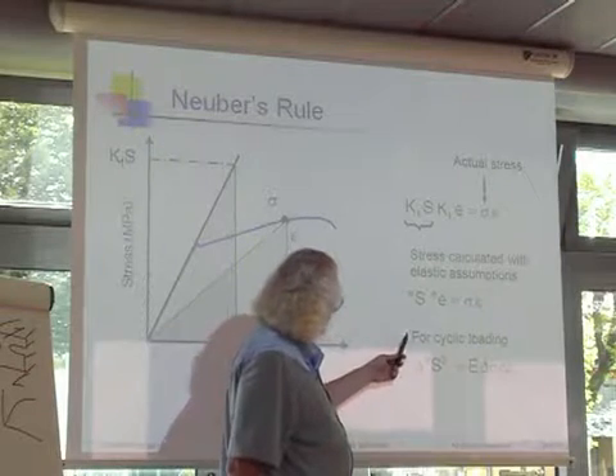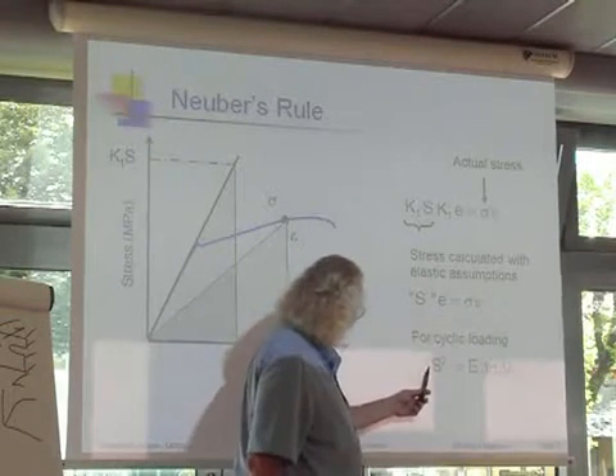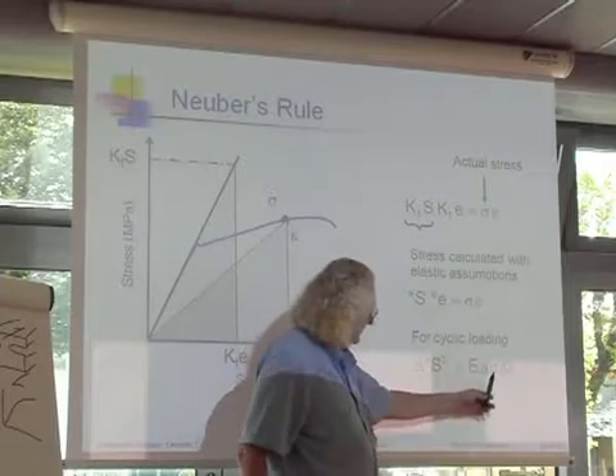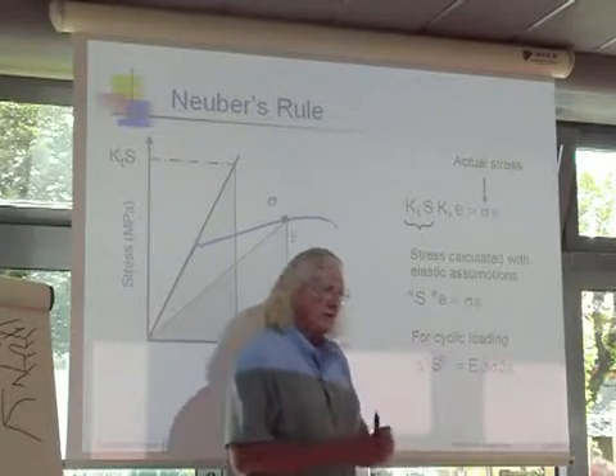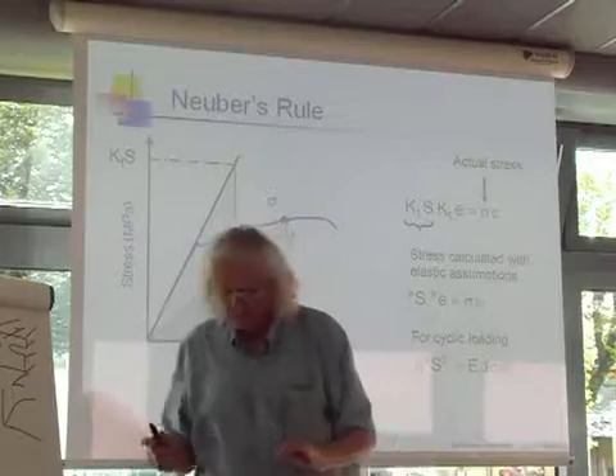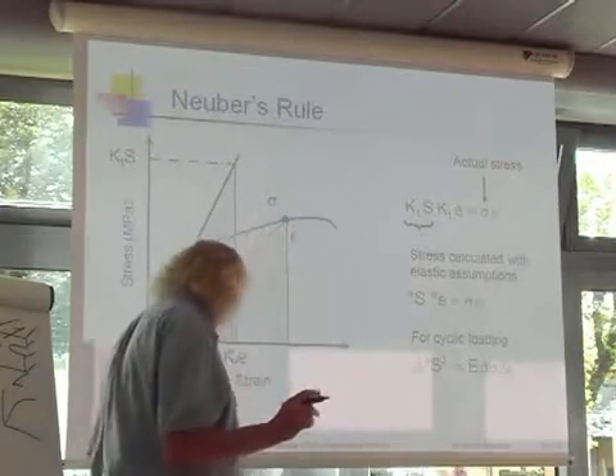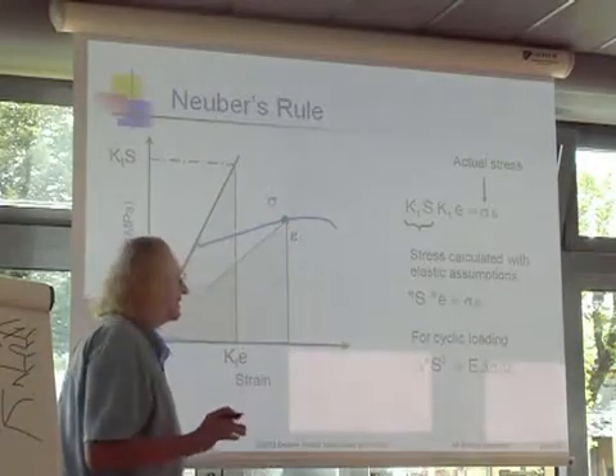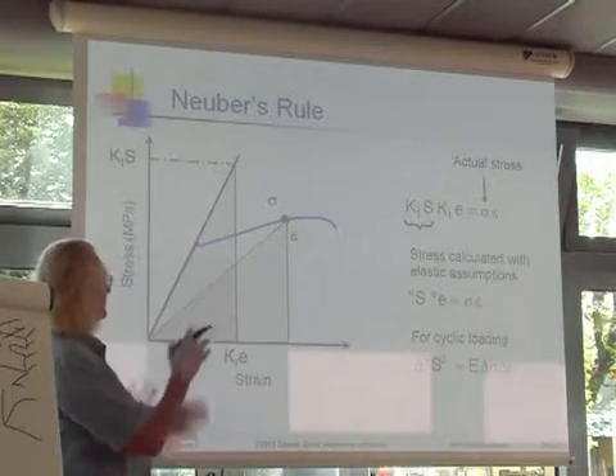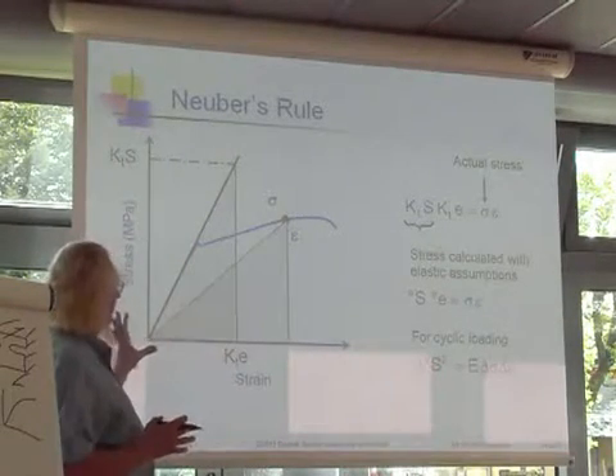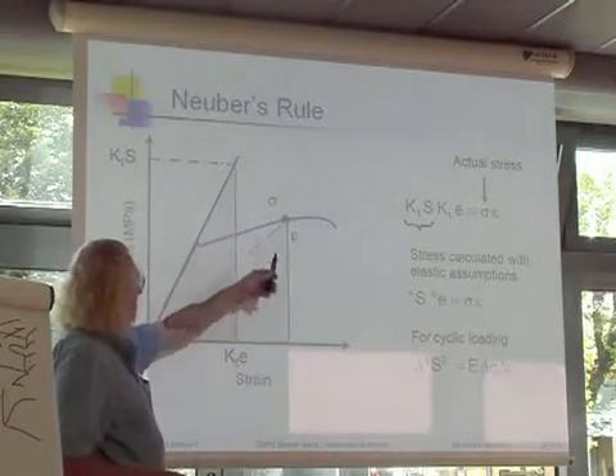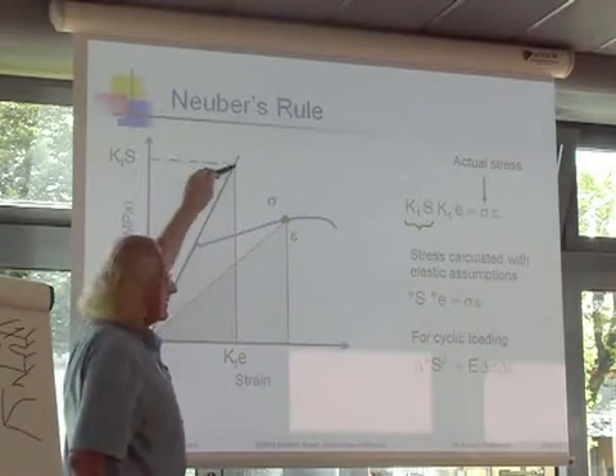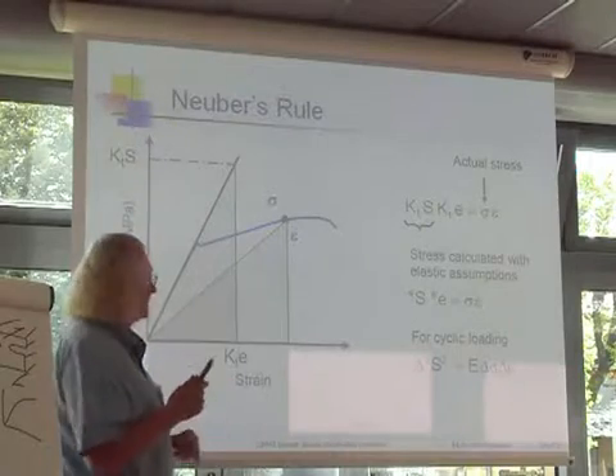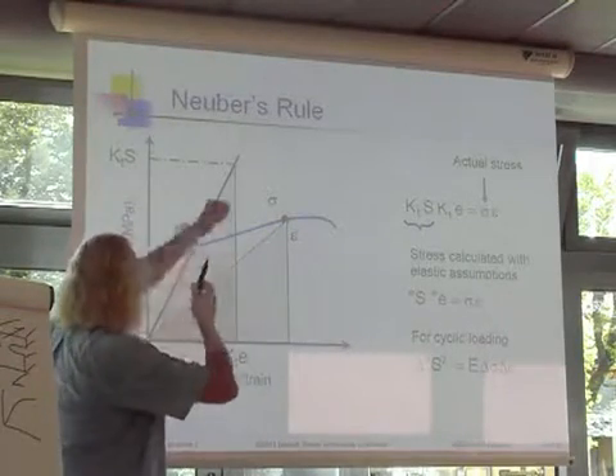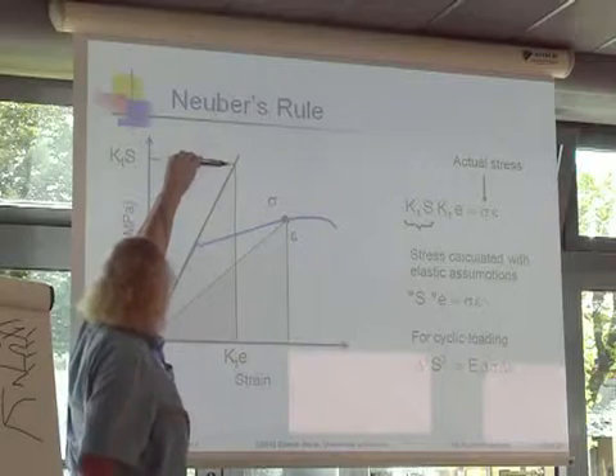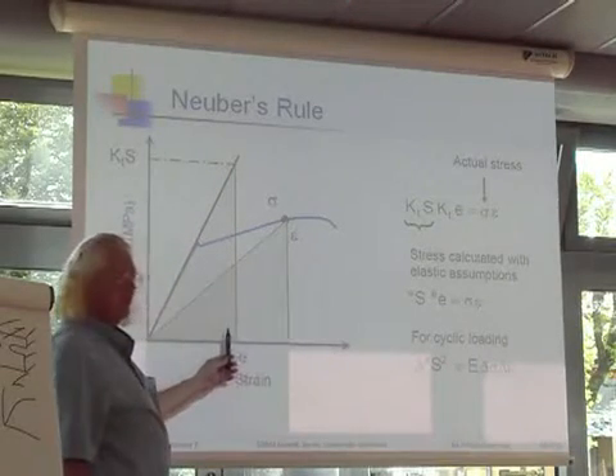And then we say, well, for cyclic loading, I just replace the stresses by the stress ranges and the strains by the strain range. So, but the idea is the product of the elastic solution is equal to the product of the real solution. So let's just look at that. So I have a material stress strain curve, and so that's shown in blue, and I have a solution way up here, because of course when I do an elastic solution it doesn't plastically deform, and so I calculate stresses which are too high, and I calculate strains which are too low.